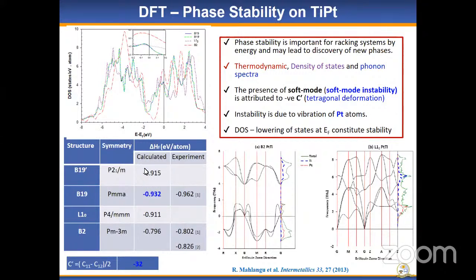So in this case, you can then relate what you have found here with the heats of formation. So you can see the B19, which is actually lying lower, and it has the most energy in terms of heats of formation. So now this has a direct agreement between the densities of states and also the heats of formation. So from there, you can move and see how the vibrational properties look. For the B2, the system that is highly unstable, you can see it vibrates quite a lot, while the one that is stable does not have soft modes or imaginary soft modes. So that's what we use to actually define the stability of the system using this simple relation.